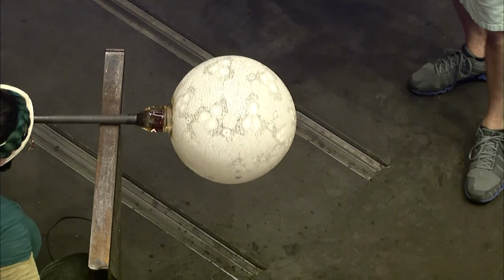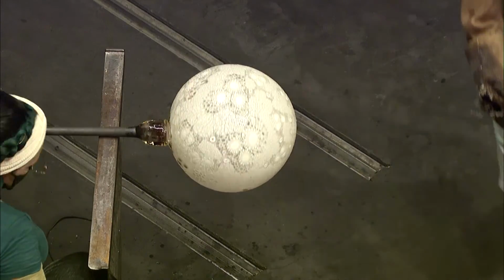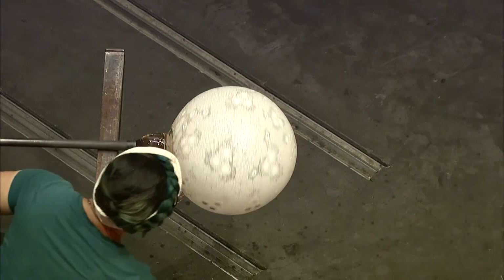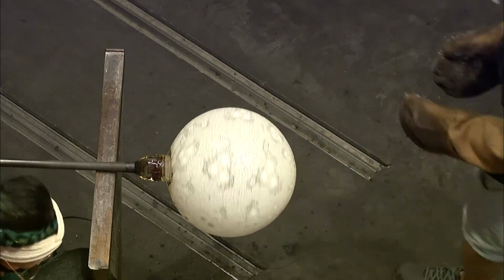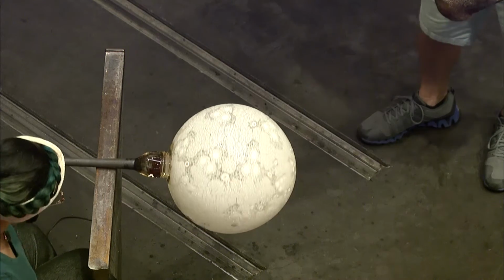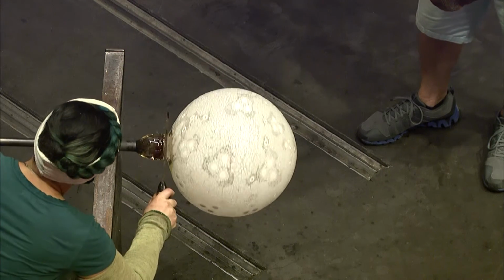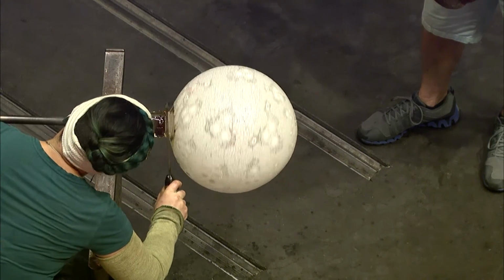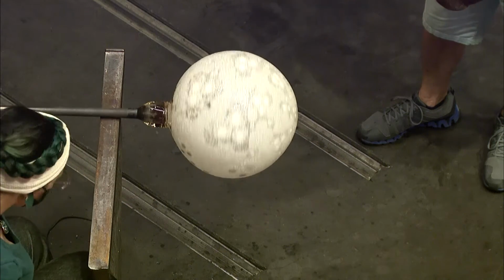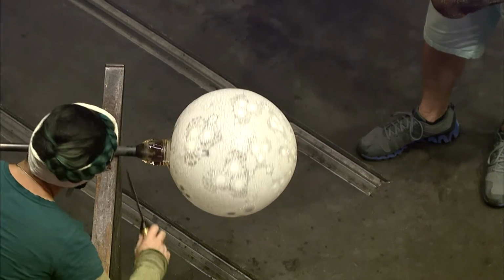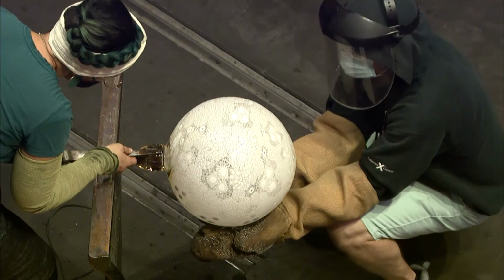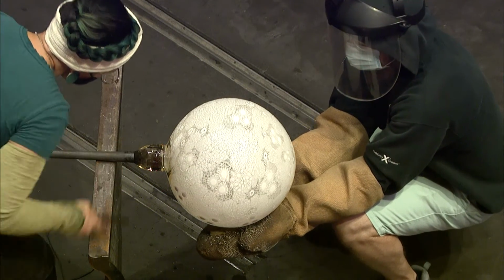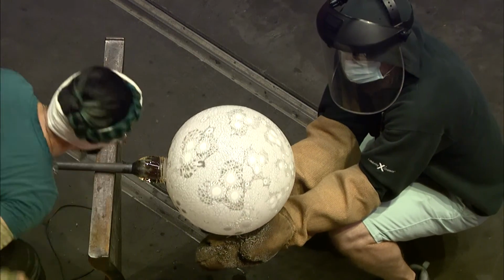So it is moving slightly, but it's moving on that constriction, which is a pretty good thing. When it's moving like that, we know that it's in a good temperature range. And you can shock that line that is still moving with a little water on a diamond file. You can score the glass. She might apply a little more water to it. And what water does at this stage is creates little stress fractures. We're really careful when we do this move not to let water touch the actual piece. One little drop could definitely ruin it.